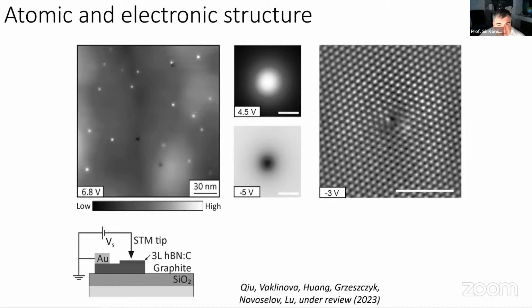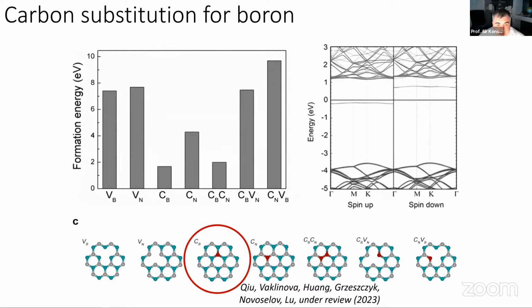So what you see now on the screen is the STM measurements. We see that there are individual defects, but it's very, very difficult to figure out what the structure of this defect is. You really have to guess which defects are the most stable upon doping with carbon. So it can be a single carbon substitution, or a combination with a vacancy, or a combination with another substitution, or with two vacancies, and so on.